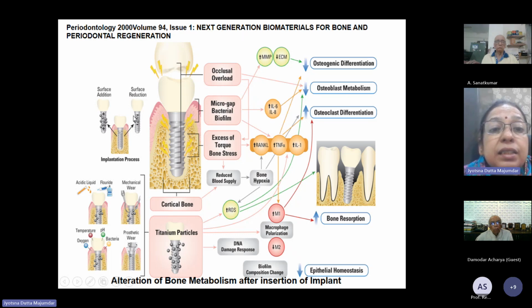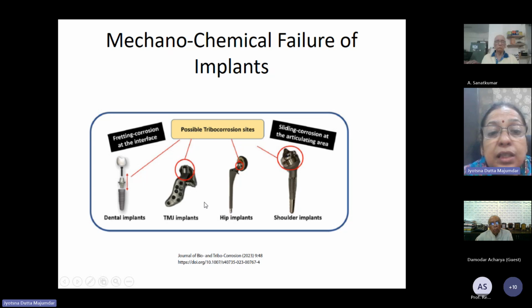Subsequently, because of this tribocorrosion and corrosion, gradually fine titanium particles come out, and they go on spreading throughout the tissues of the human body, causing inflammation and allergic reaction. These problems are always there in the human body after 5 to 6 years of implant. So these are typical examples of mechanochemical failure like fretting corrosion at the interface. Fretting corrosion is another kind of corrosion persisting in dental implants.